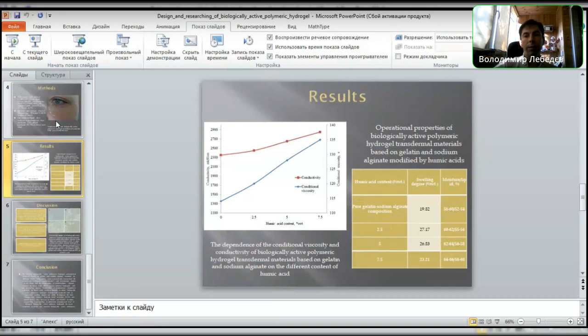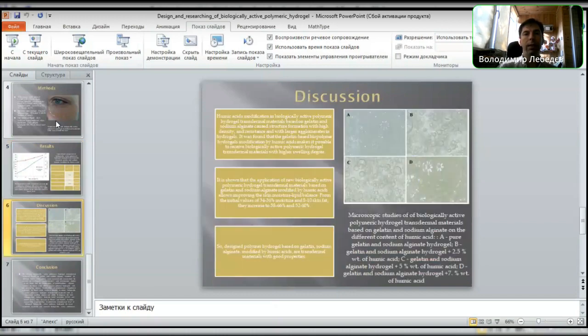So modification by humic acid makes it possible to obtain hydrogel transdermal materials which, when applied to the human body, will allow regulating the moisture-lipid balance of the skin uniformly and for a long time. In fact, as shown on slide 6, with biological active polymeric hydrogel transdermal materials based on gelatin and sodium alginate modified by humic acid, it becomes possible to transfer the skin from a slightly moist, fatty, hard condition to a highly moist, fatty, elastic condition. The improvement of the moisture-lipid balance of skin increases with increasing humic substance content.